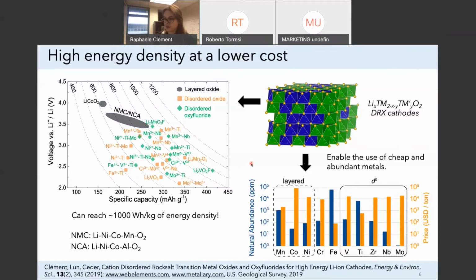Perhaps the most important aspect of these materials is that we can now use cheap and abundant metals. So we are no longer constrained by using manganese, cobalt, and nickel. We can now start exploring compositions where manganese is the only transition metal that is redox active, and we need to combine this with one of these d0 metals to stabilize the disordered structure.